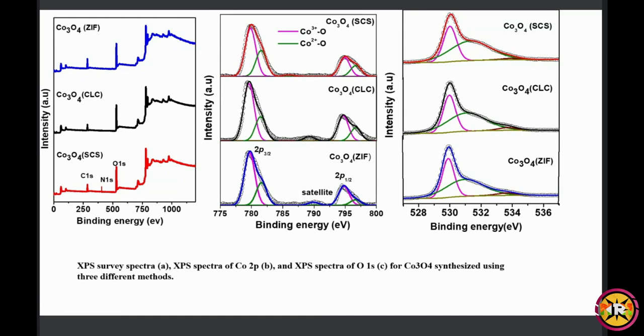This is the oxygen 1s XPS, and here you can see at 530 electron volt one peak is there. This is for lattice oxygen, and at 531.5 one peak arrives. This is for oxygen vacancy. So from XPS also I have shown the formation of the oxygen vacancy, and I have calculated the amount of oxygen vacancy by OV by OT calculations, and there also I saw oxygen vacancy is higher for SCS.